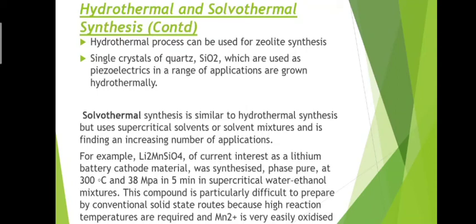And solvothermal synthesis is similar to hydrothermal synthesis, but it uses supercritical solvent mixtures, and it offers an increased number of applications. For example, Li2MnSiO4, of current interest as a lithium battery cathode material, was synthesized phase pure at 300 degrees centigrade and 38 MPa in 5 minutes in supercritical water-ethanol mixtures.